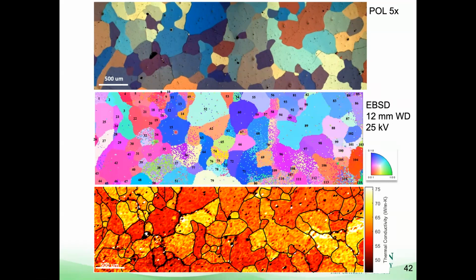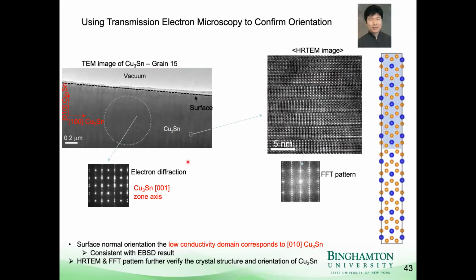So we also did transmission electron microscopy just to confirm what we saw was correct. We looked at these two grains, 15 and 62, with transmission electron microscopy, with help from the ADL, particularly Dr. Intebe. So this is grain 15, and this is the side view. We did something called focused ion beaming to make a little fin of Cu3Sn, and then we put that fin inside a transmission electron microscope and looked at it. So this is a high resolution TEM map. You might see kind of striping, a pattern of stripes vertically. Well, this is actually the tenfold superlattice that we can see through TEM images.